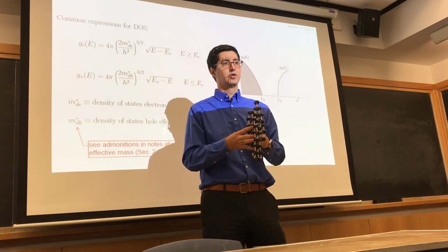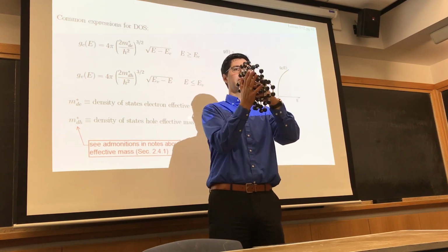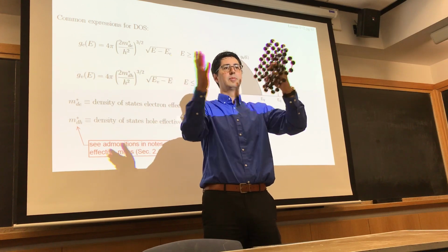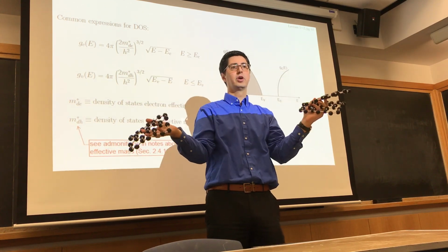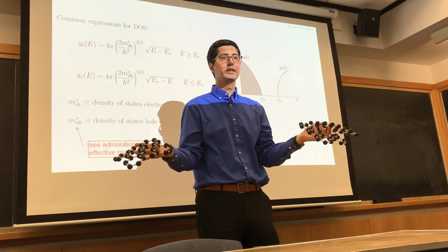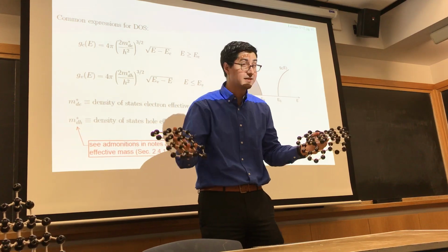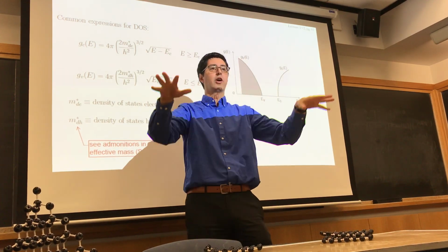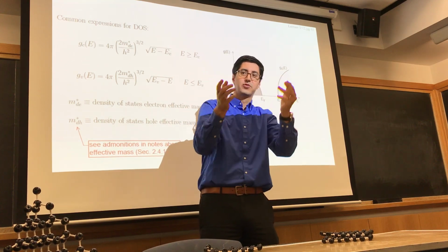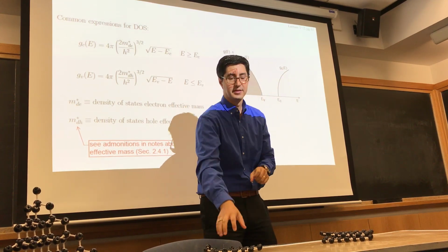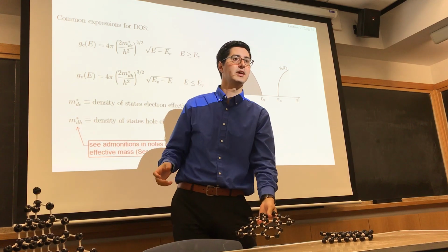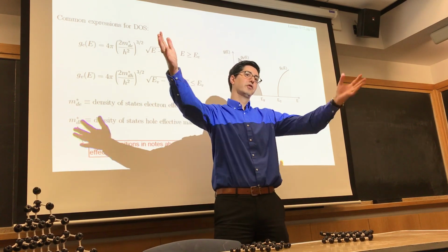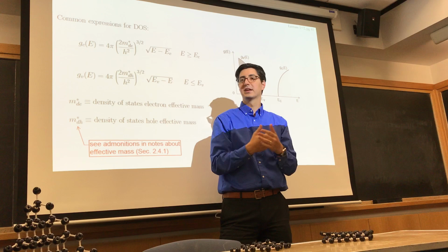So they took Scotch tape, you kind of put the crystal in between it and you pull it back a couple of times, and every time you do it, you separate the layers more and more. And then probabilistically, if you look across that tape, sometimes there are little flakes that are just a single layer. Not every flake is a single layer. A lot of them are really thick,